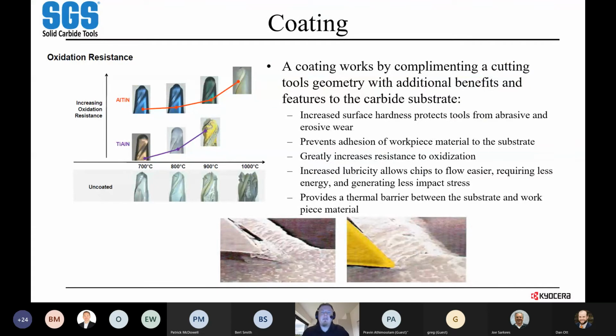Next up is coating. Coating is going to work by complementing the cutting tool. It's going to take whatever your tool was originally doing, and it really just enhances that. So: increased surface hardness, preventing adhesion, resistance to oxidization, adding lubricity into the cut, and then of course providing a thermal barrier between the substrate and the workpiece. You can see the chart here. This shows an uncoated tool at various heat points compared to coated tools. And I mean, there's a pretty drastic difference there.